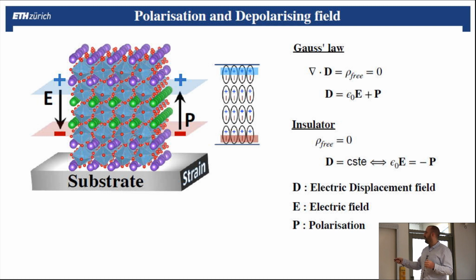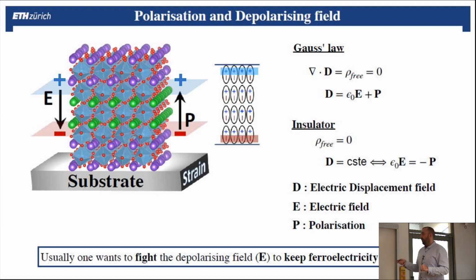So Gauss law says that the divergence of the electric displacement field, which is defined here, is the sum of electric field and polarization, has to be equivalent to the amount of free charges that you have in your system. But if this is an insulator, then you don't have free charges. The free charges are zero, and that equation means that the D has to be constant. So to be constant, it means that this part should be equal to minus this part. And this is what happens in your heterostructure. You have the polarization in one direction and the depolarizing field or electric field in the other direction. It's called depolarizing field because it cancels the polarization in the system in order to remove charges here.